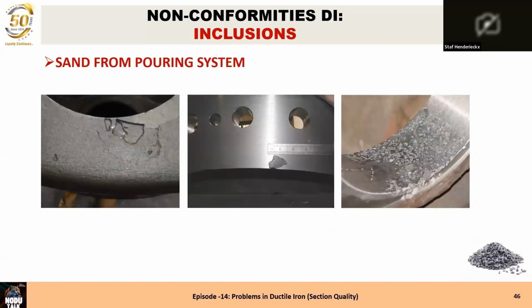Sand from the pouring system, there is something very, very well seen. On the left side, you can see an inclusion of bigger sand, there is always a straight line. And when you see a straight line, you can be sure that it's sand, because the sand was bent, broken out, and that breaks always at a straight line. In the center, you can see the same. When you see some straight lines, it's a big sand that comes out.